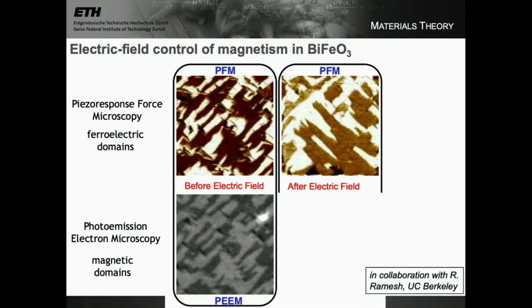So then we apply an electric field to this material, and the electric field, of course, will affect the ferroelectric domains. The electric field will couple directly to the electric dipoles and reorient them. And what you see is that the pattern changes. When I said this data is very primitive, you see that it doesn't change at this stage very systematically, right? But it certainly changes. And now we have a different arrangement of electric dipoles after we apply an electric field.